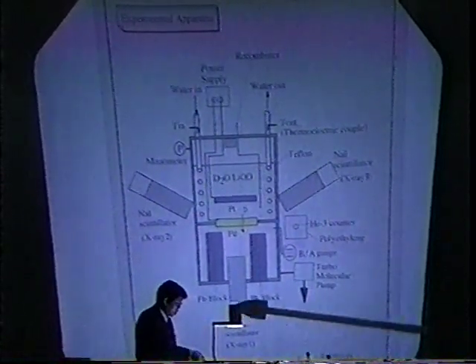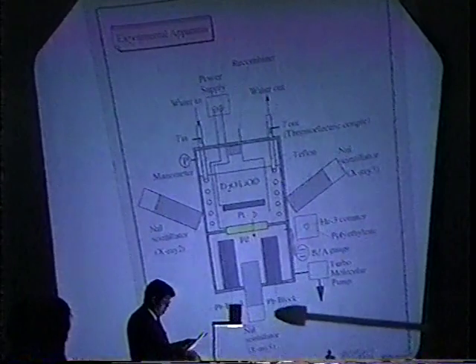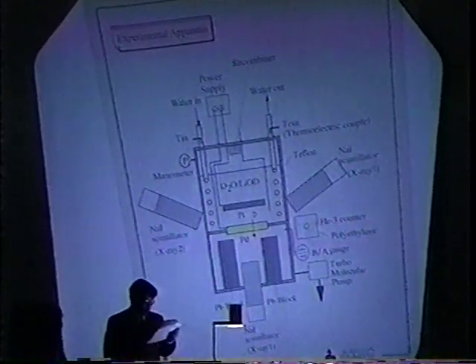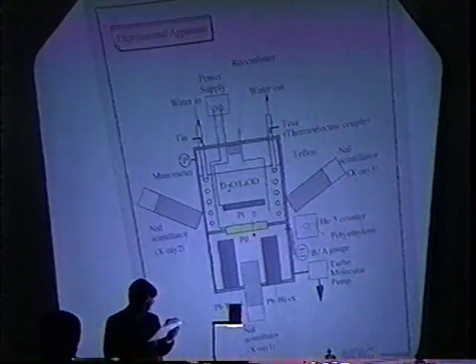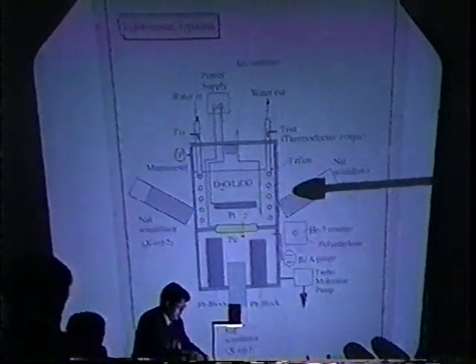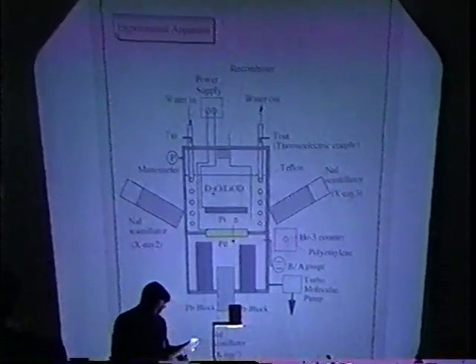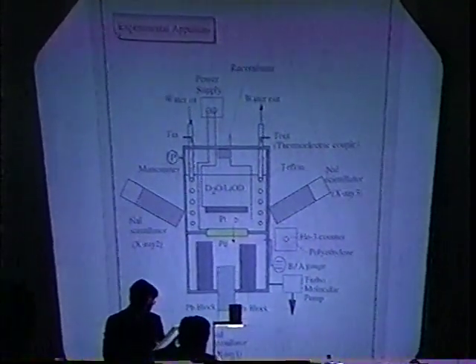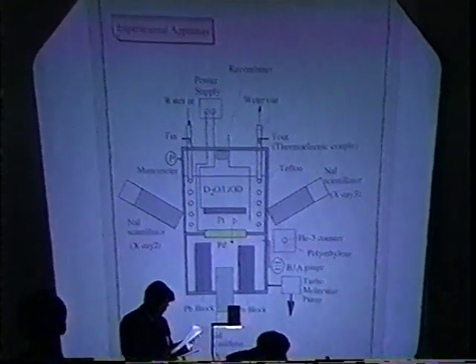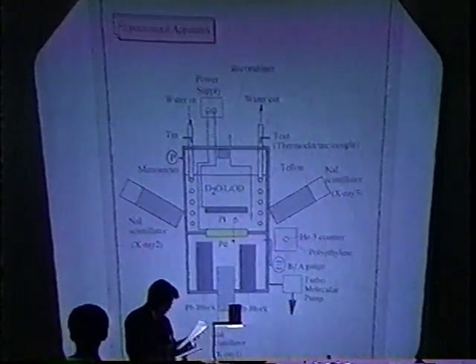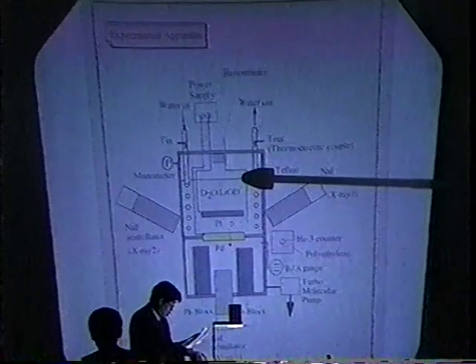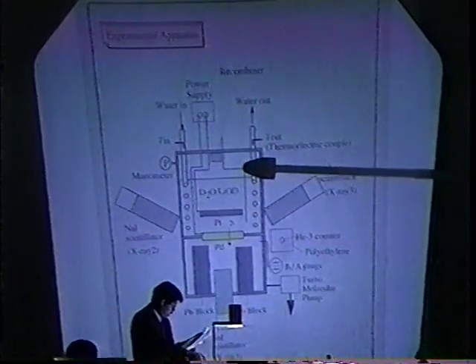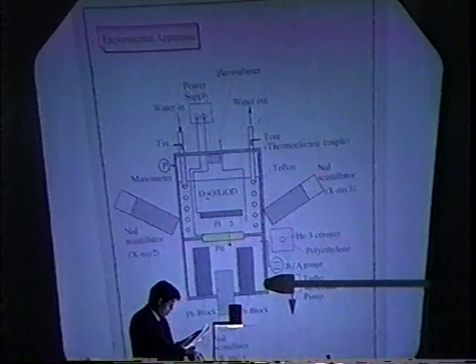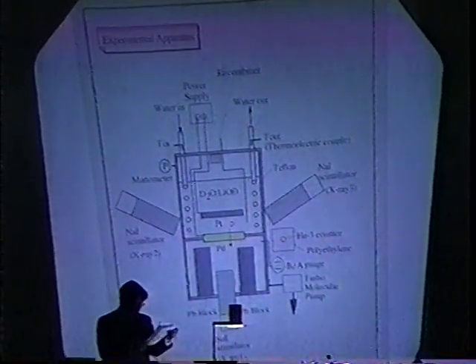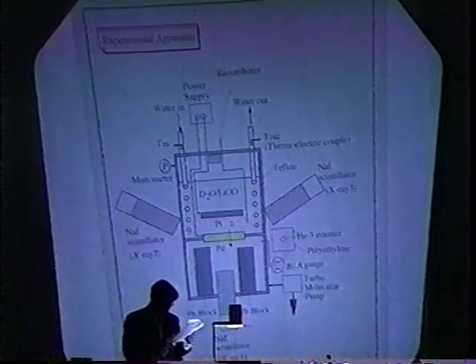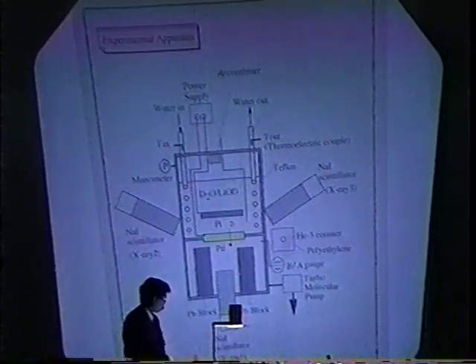The first NaI detector is surrounded by a lead block to reduce the background X-rays. The second and the third X-ray detectors are located outside of the cell, looking at the surface of the palladium. And we have measured the pressure of the upper side, the electrolyte side, and the pressure of the vacuum chamber in order to estimate the absorption and desorption of deuterium through palladium.